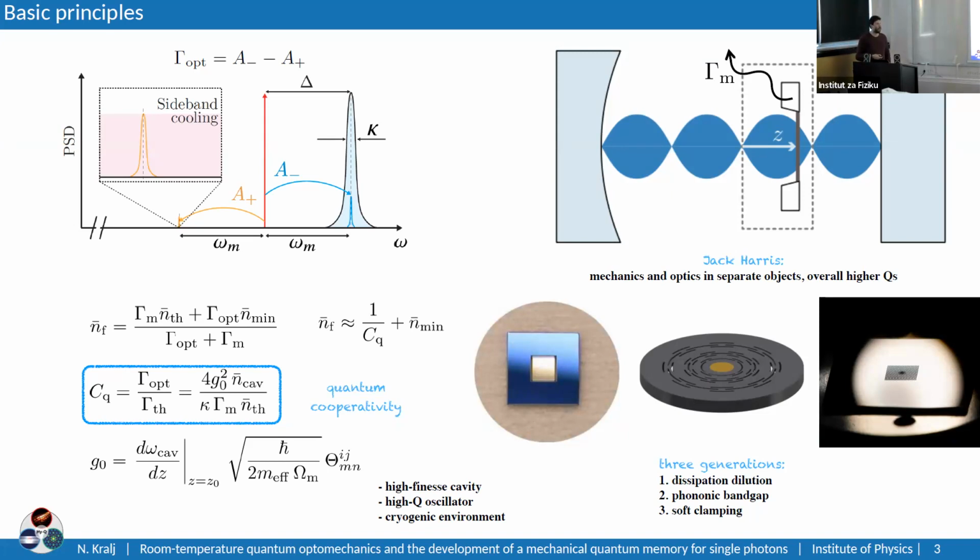And then people had the idea of some sort of phononic shielding. So the first iteration of the phononic shield in this sort of membrane: the difference between these two is that this one, the brownish looking thing here, is basically the window, which is the silicon nitride, and it just so happens to be circular. In this case, that doesn't matter. But the grayish thing around it is the silicon wafer. And as you can see, there is some sort of periodic array of holes. Basically what this does is it opens a band gap at a particular frequency region around some modes of this circular thing that are of interest to you. And this band gap radiatively shields these modes from the outside and vice versa. And this boosts the Q factor.